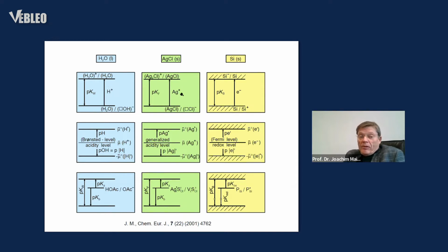And this also may, in some cases, be 0, this kind of gap. Then we speak of a superionic conductor. And we will later meet one of those, this rubidium silver iodide, where this gap is virtually 0. So every silver ion is then disordered.